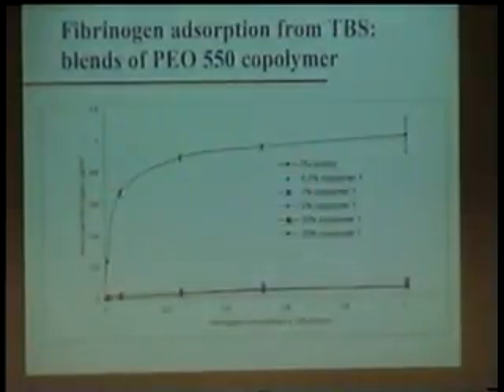And if we do that experiment I just mentioned in the previous slide, this is kind of typical data that we get. This is adsorption from buffer, tris-buffered saline, and there are blends of this copolymer where the PEO molecular weight is 550.